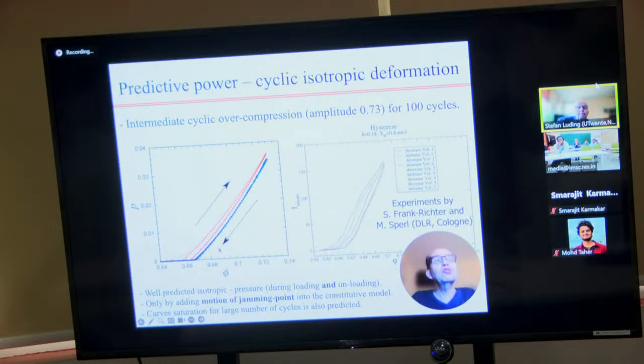Now, on the left you see pressure, some of the data. The points are particle simulations, the lines are the continuum theory from 2016 actually. We had a quasi-static continuum theory at that time which worked pretty well. And the right data are experimental data. Soft hydrogel particles which confirm the loading and unloading jamming density is not the same.